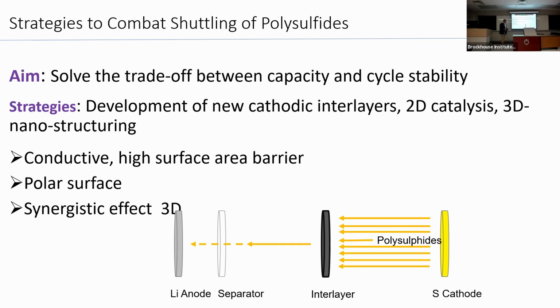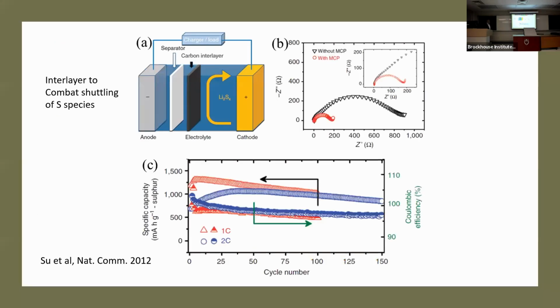But now if you're doing materials chemistry day to day, you can think about various materials that will actually act as an inhibitor of shuttling. Now this is an example. There was a carbon interlayer. This was accidentally found that a carbon that was put as a material actually led to this advantage that the capacity was stable and was very, very predictable.